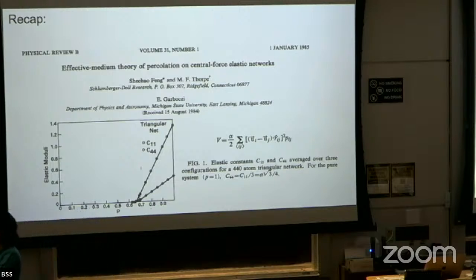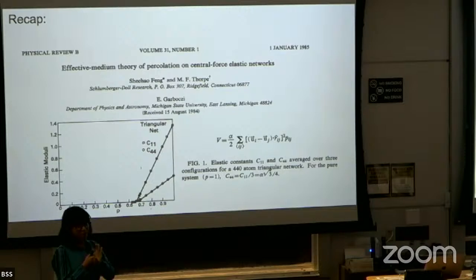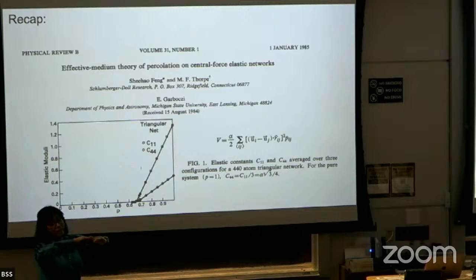You could look at finite size, shear modulus at a finite scale. And so as you go to a larger scale, as you approach closer to transition, that scale where you lose your shear modulus will get larger and larger. Oh, yeah, and that made me think of something else. Yes, there is another quantity we often look at. We look at something called a non-affinity parameter. And this non-affinity parameter also will show divergences at the shear modulus. You can calculate that quantity everywhere, right?